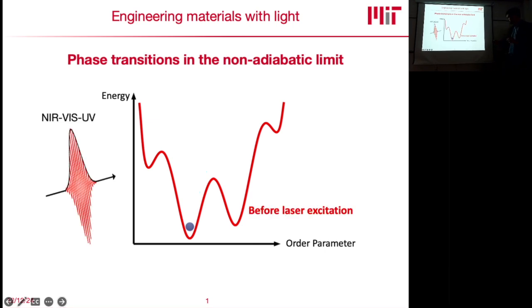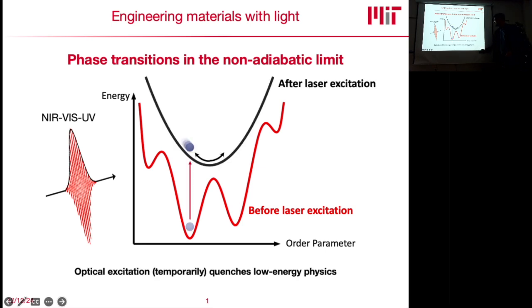So what people have done in the past to access these minima is to use ultrafast laser pulses, usually in the near-infrared, visible and UV light, where they quench the low energy ground state and promote the system into something that resembles the high temperature ground state, and then potentially also excite these coherent oscillations. And then during the relaxation of this material, it can actually end up in one of these adjacent minima, which persists long after the laser excitation. This is usually how people would drive these ultrafast phase transitions into one of these hidden states. However, since we are now relying on this relaxation process, over which we don't really have a lot of control, this is pretty non-deterministic.